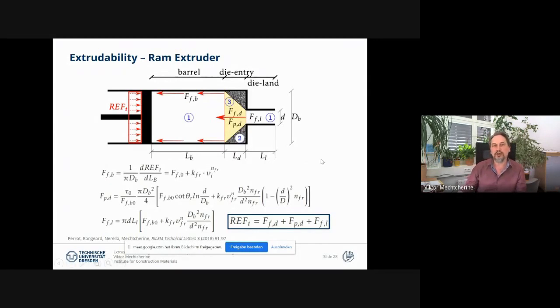Okay, of course, also here some formulas can be very helpful. You see here the formulas for predicting the forces needed for actually extruding material by using a ram extruder. And here it looks really good. We have quite clear formulas, which I will not explain in detail, but you can find them in the literature, which is given here. So you can really link the extrusion rate to the extrusion forces directly. However, we do not really use a ram extruder in practice very much because it's not really suitable for large geometry, for large printing.